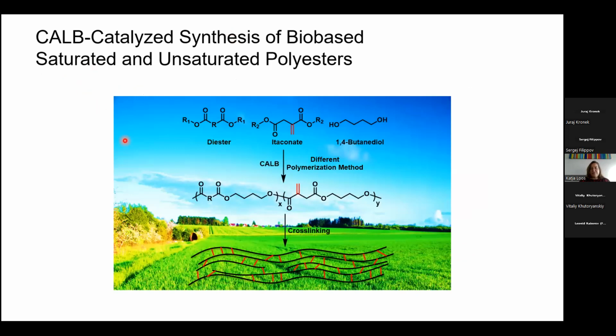And one thing I wanted still to show you before I switch to the furan-based polymers is another textbook example why enzymatic polymerization is interesting. It's the polymerization of itaconic acid or itaconic acid esters. And for those of you who have worked with this monomer before, if you want to do the polyester from this monomer, and you do a melt polycondensation, the temperatures are too high, and then radicals will always be formed, and then you have a radical reaction on this double bond, and you have automatic cross-linking.